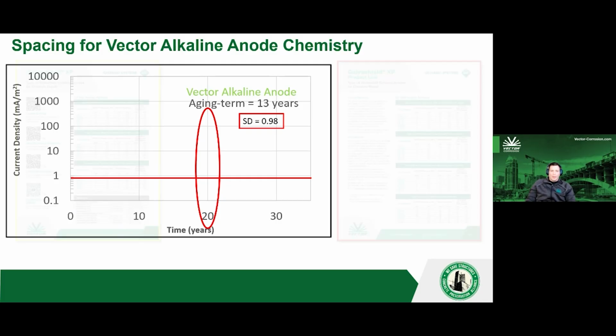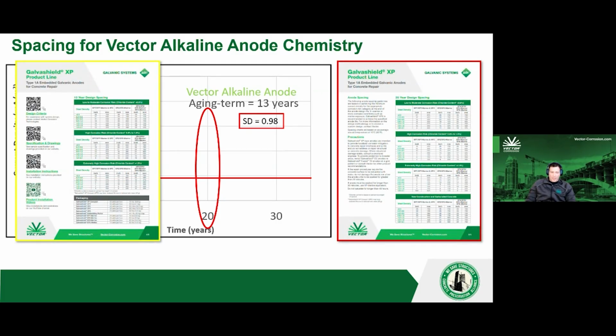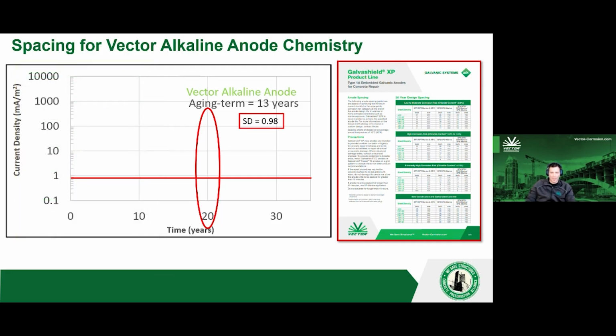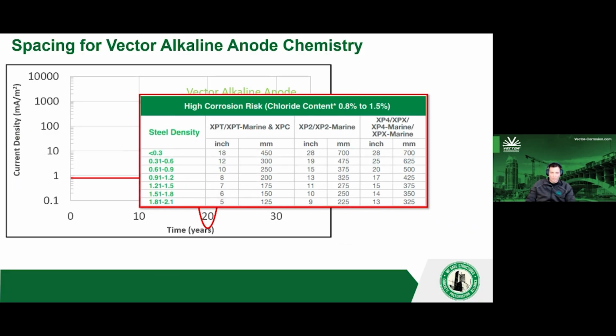Now, here's the 2 spacing charts I talked about. This is on the technical data sheet. We have ones for a 10-year design as well as a 20-year design, depending on what you're trying to do. We've determined in this case, we're looking for a 20-year design. Okay. We are in the high corrosion risk, so we have to choose that off the chart. And then within this high corrosion risk, we know what our steel density is. It's 0.98, so it falls into this category.